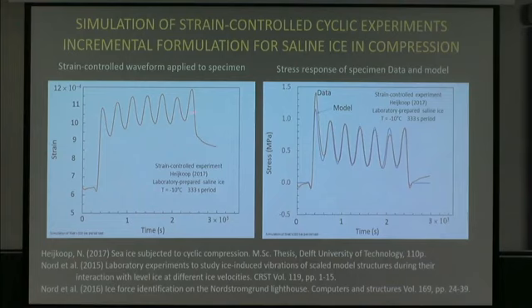Model data is still in red, my model's in blue. It's a little bit off here, and I think that's probably more a result of filtering on the input than anything, because it does a pretty good job everywhere else, but there's a bit of a jolt to the loading at first that was real, but I think it got filtered out of the strain data, but the stress data still reflected that. At any rate, we weren't sure of the dislocation density, so we had to play around. He had kind of low salinity ice, but basically I thought it did a real nice job. The only thing we had to do was set the dislocation density, and then everything else required no tuning, it was fixed. So I was happy with that.